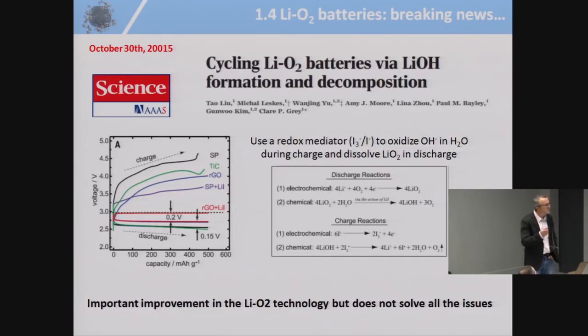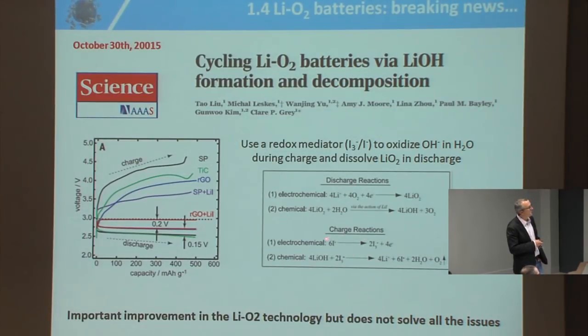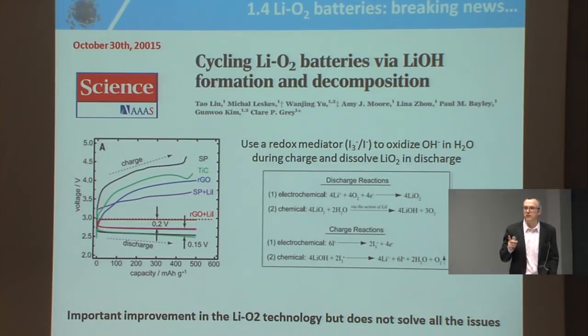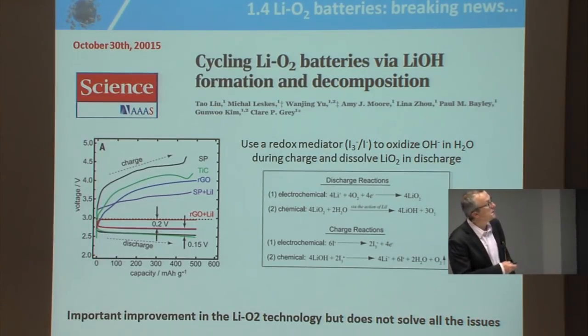How did they do? Well, just a bit of science. They just used a redox mediator, iodine. And this iodine here, during the charge, you are going to form I3-, and this I3- is going then to oxidize OH- in water. Then you remove all the polarization, let's say. But this is a very interesting concept and a tricky idea that can be very interesting for the future of lithium, but this does not solve the appearance of the superoxide ion. So it solves a part of the problem, but this is not the solution. But this is very interesting.